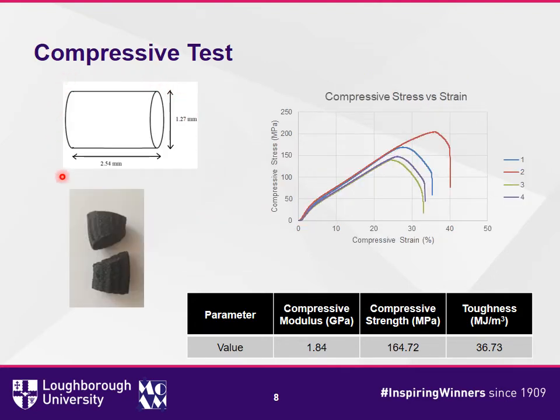The compression test of the material was also carried out as per ASTM D695, and the following compressive stress versus strain graph was obtained. From the graph, it was found that the compressive modulus of the material is around 1.84 gigapascal and the compressive strength is 164.72 megapascal. The average compressive toughness is approximately 36.73 megajoule per meter cube. Examining the sample after the test revealed buckling before failure, which dictates the poor performance of the material under compression. In future, the aspect ratio of the sample needs to be changed and retested under compression.